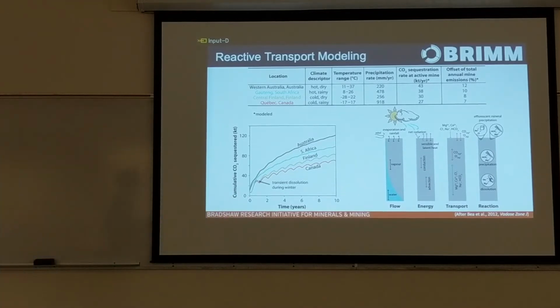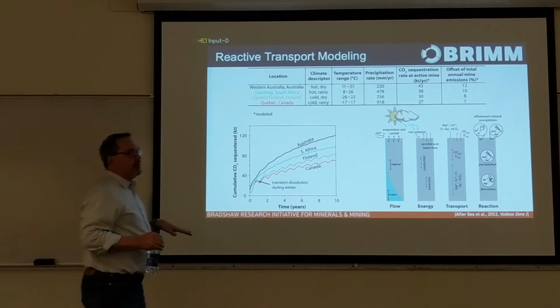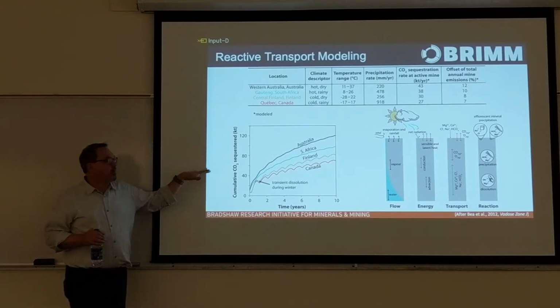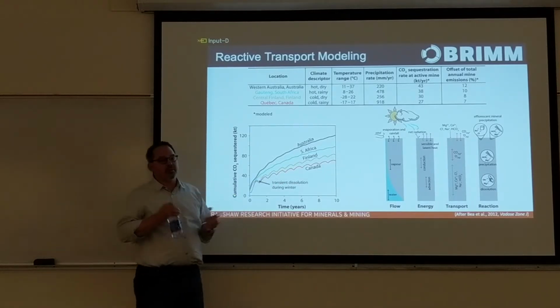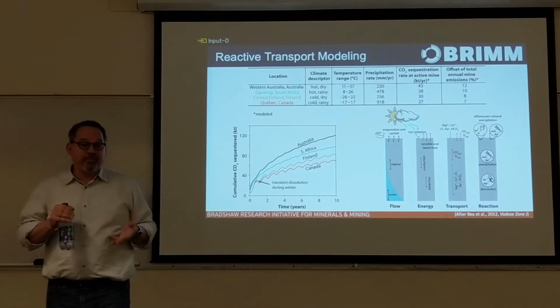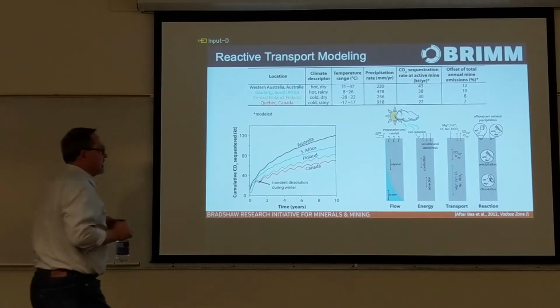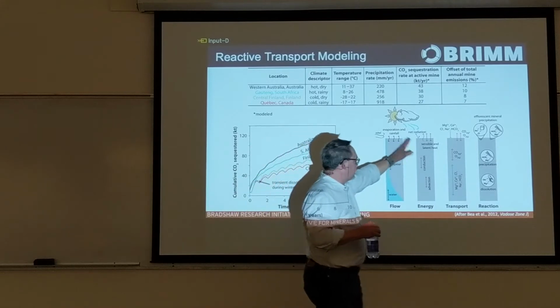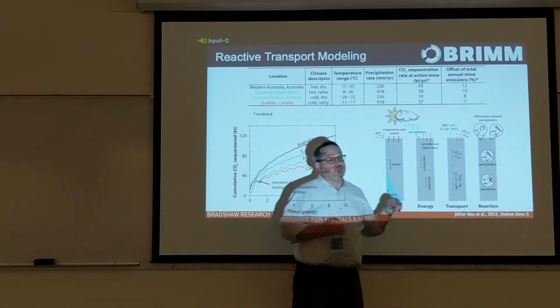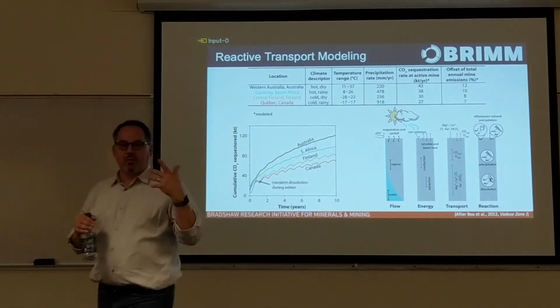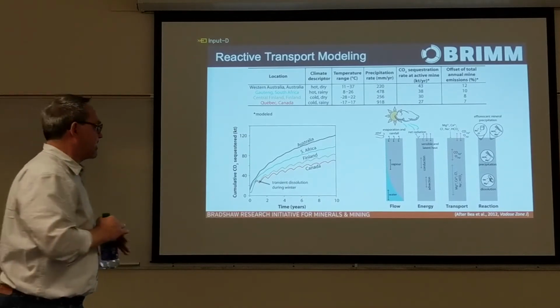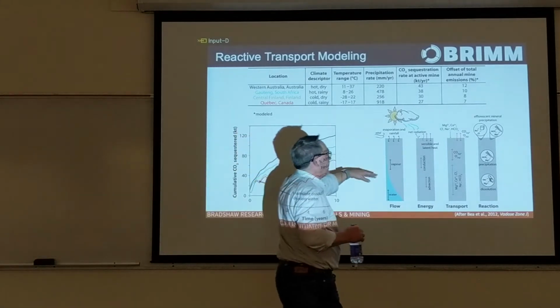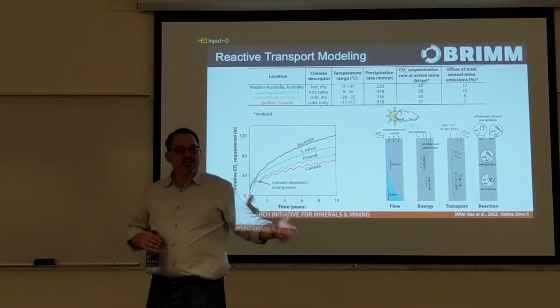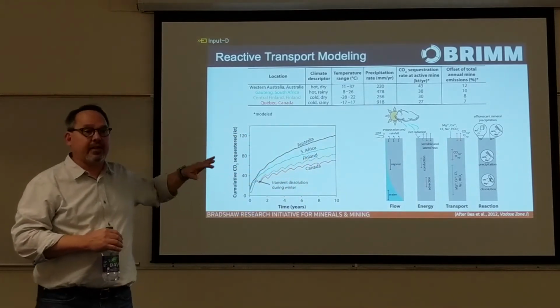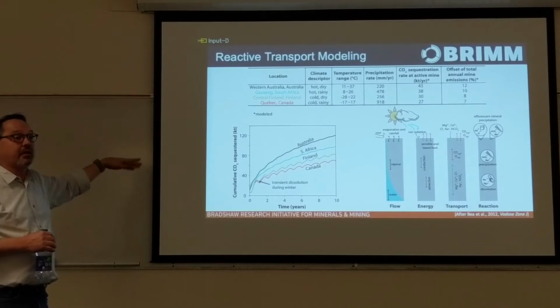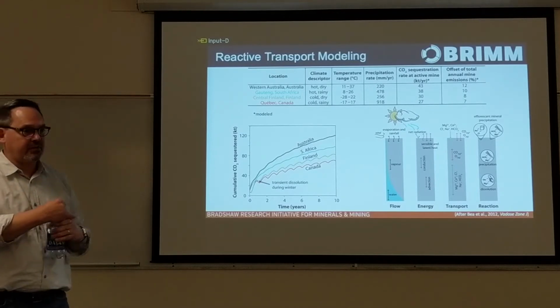So this reactive transport model is essentially a bathtub filled with sand, filled with water. We're evaporating the water out. We impose a climate cycle on it. We track temperature, latent heat, crystallization, and evaporation. We have all the sensible heat. We have advection, diffusion and advection of gas, liquid transport, mineral dissolution, precipitation, kinetics, all embedded within here. And then we can make predictions on how this, just to illustrate, being the control, everything else being constant, this is the control of climate on the passive rates of carbon fixation that would happen.